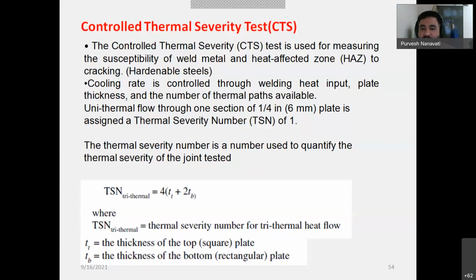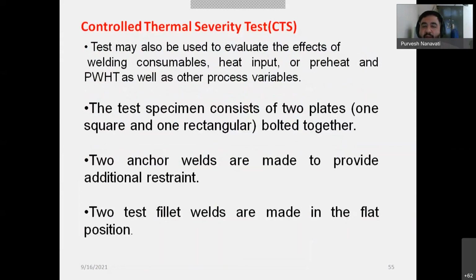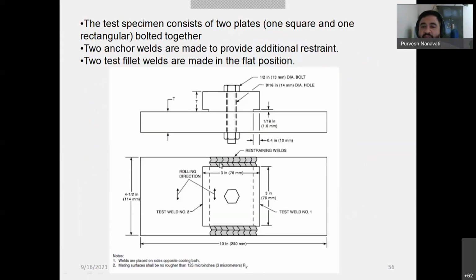So TSN, it means when the thick sheet is there, the heat along the thickness and depth direction will be dissipated. Using this formula, you can calculate the thermal severity number, but you can consider 1 for the 6 thickness. So how will the controlled thermal severity test setup look? You just weld this test piece with the anchor weld. These are known as anchor welds, and also as restraining welds, because here you are restraining the heating and cooling of the weld, right?